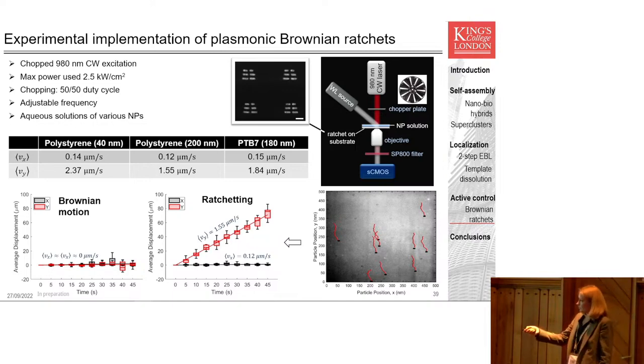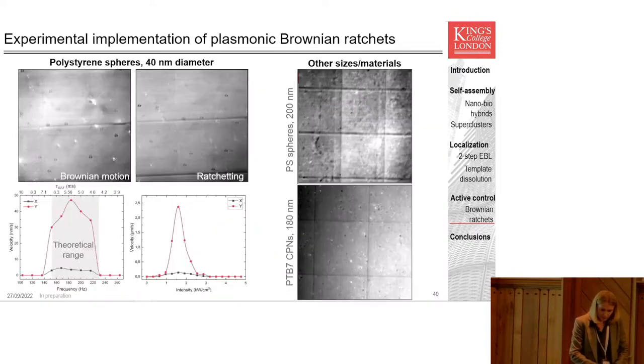So to show you, this is a control experiment of Brownian motion of nanoparticles. You can see that in general, they will have some displacement from zero, but on average, you have absolutely no preferential direction for motion, as opposed to the case where we are actually ratcheting. So we are rectifying Brownian motion, where the velocities along the y direction are a lot higher than the velocities along the x direction. And we've tested it for several different nanoparticles, mostly polystyrene polymeric nanospheres, because they're easier to track.